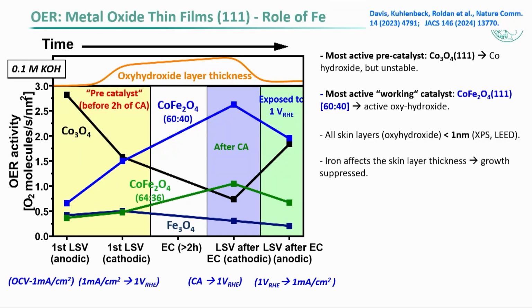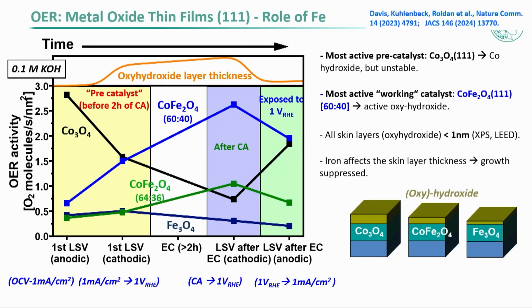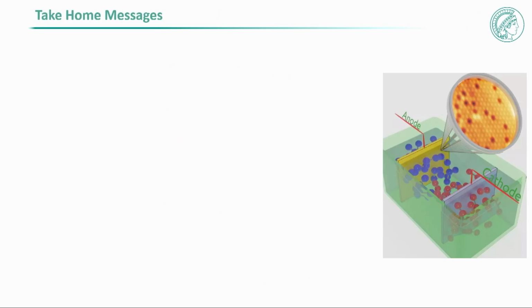What we learn also with this detailed characterization is that the thickness of the active component of this catalyst, this oxyhydroxide layer, depends on how much iron I add. And if you have a lot of iron, I have a thinner oxyhydroxide layer. So these are the things that I wanted to tell you about today. So I will give you some take-home messages.